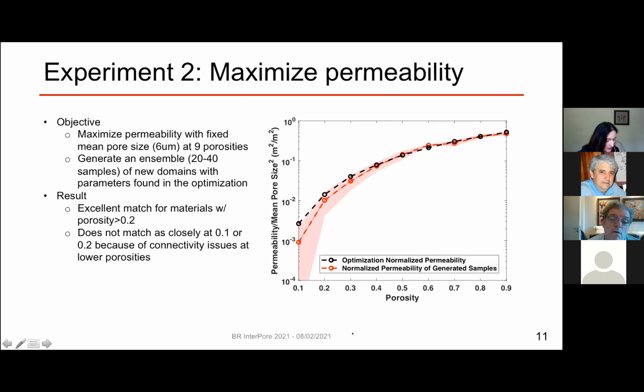For the second experiment, our objective was to maximize permeability with the fixed mean pore size at 9 different porosities. So here are again porosities from 0.1 to 0.9. The black line is the target permeability that we want to achieve, and the red one is the average of our ensembles, and this red cloud shows 1 standard deviation. We have an excellent match for materials with porosity of greater than 0.2. So from after 0.2, we have very good agreement.